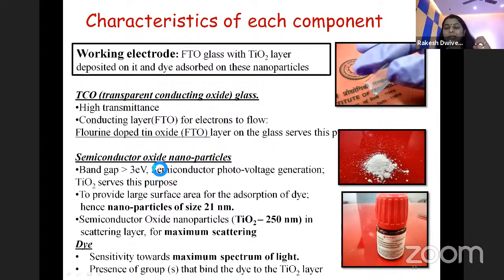As most students in this group are here, I wanted to tell you what parameters you can play with to get an efficient solar cell. For the working electrode, we are simply using FTO glass, that is conducting glass, on which we deposit the TiO2 layer and adsorb the dye onto the TiO2. Now, what parameters can you work on? Like this FTO glass, you can try to replace it with some flexible material.